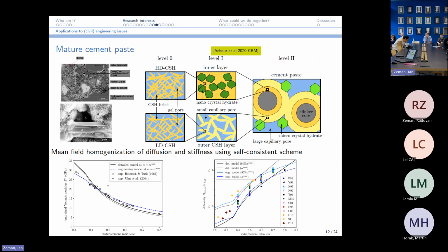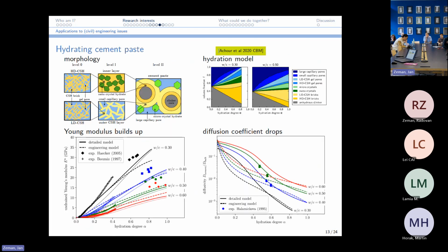And that is because of a dilution effect, but also because of interaction of ions with the surface of the CSH gels here, which are nanometric scale pores with a high surface. So using that and combining it with the hydration model to see the evolution of the volume fractions of the constituents with time. As time hydrates, you would consume water, reduce porosity, and produce new hydrates. So your Young modulus would increase and your diffusion coefficient would drop. Okay.